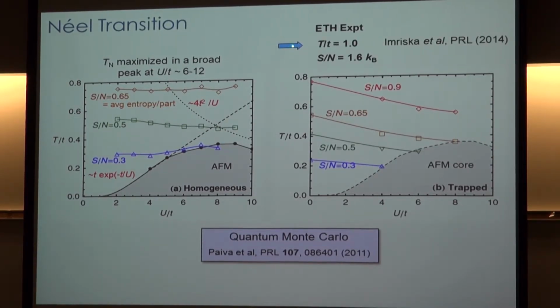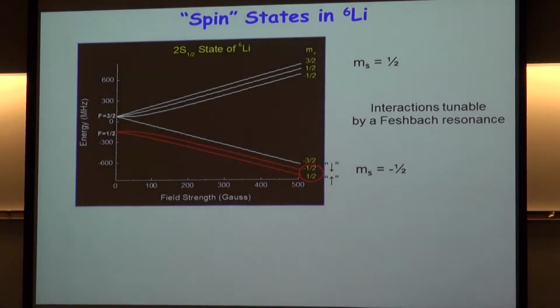Just for reference, this is where the ETH experiment, the current experiment, is, with temperatures of about 1 in these units, which is about a factor of 2.5 above what it needs to be, and entropies that are also about a factor of 3 or so higher than what is needed to get into the Néel phase.